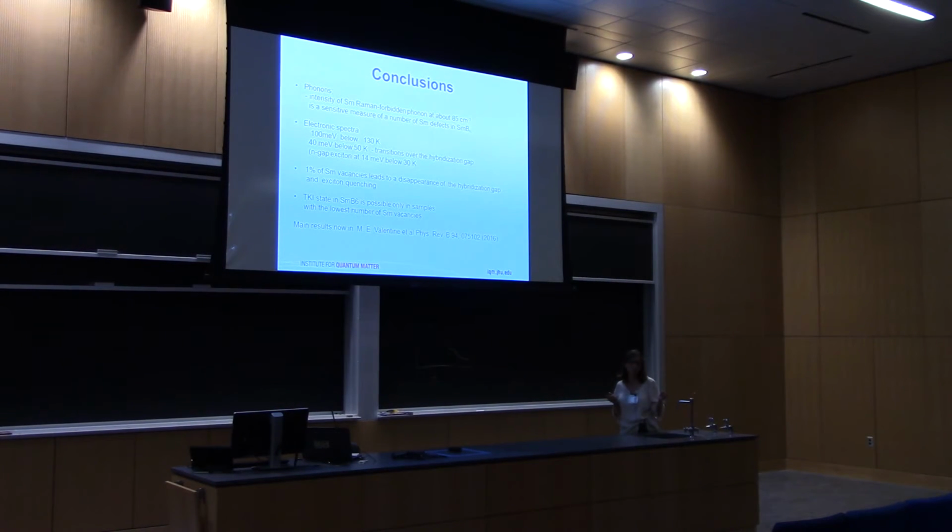Less than 1% of samarium vacancies will start to put states inside the gap. And I think the variety of results in the field might depend on the fact that it's very difficult to identify very small amounts of samarium vacancies, yet they can bring some bulk metallic response. Okay, thank you for your attention.